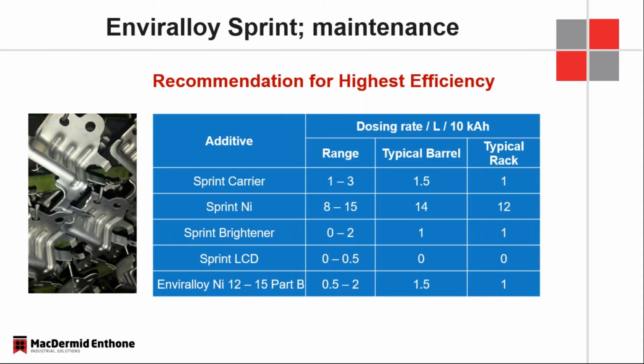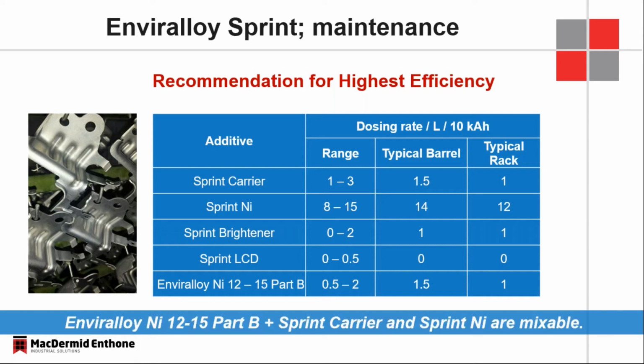So what are we talking about for dosing rates per 10,000 amp hours? If you look at the first item being the Sprint carrier at 1.5 liters and the Enviralloy 1215 Part B at 1.5 liters, that's 3 liters per 10,000 amp hours. In the previous system, before our upgrade in technology, we were looking at rates of more like 4 to 5 liters of carrier per 10,000 amp hours. So we have significantly reduced the cost of operation for the applicator. Again, this is all relative according to drag out, rack versus barrel, and throughput. As mentioned here, it might look like a lot of additives, but we really can mix the nickel, the carrier, and the Part B on one feeder, a second feeder for the brightener, and then the LCD would only be added as needed per hull cell analysis.